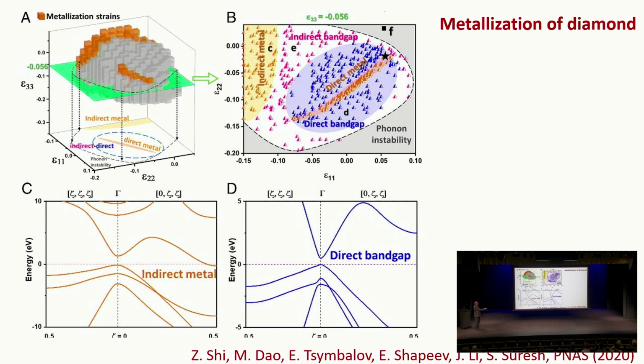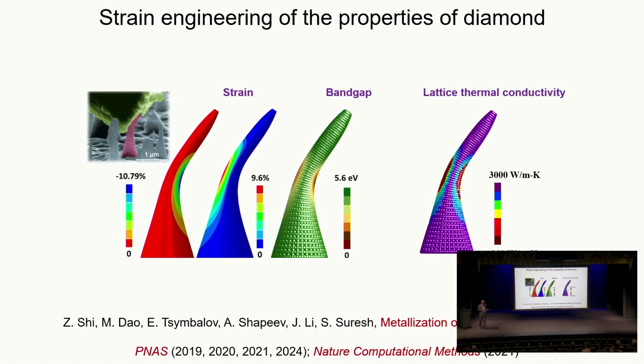So you have direct band gap, indirect band gap, and I don't want to go into the details of this. You can also look at the energy space, and you can look at the energy spectra and so forth to show where the band gap occurs and how. In addition to changing the band gap, diamond also has very interesting thermal conductivity properties. So lattice thermal conductivity of diamond, just from the bending experiment, can be changed from 800 to 3000 watts per meter Kelvin, the units that we use here for thermal conductivity. So in some cases, for very high strains, you can actually change it by 2 orders of magnitude, both in tension and compression.